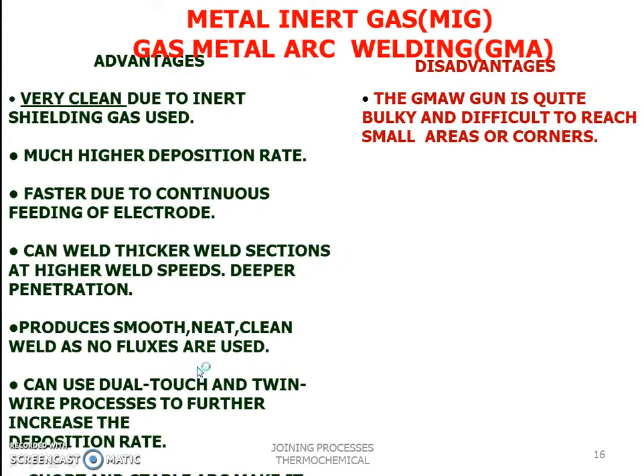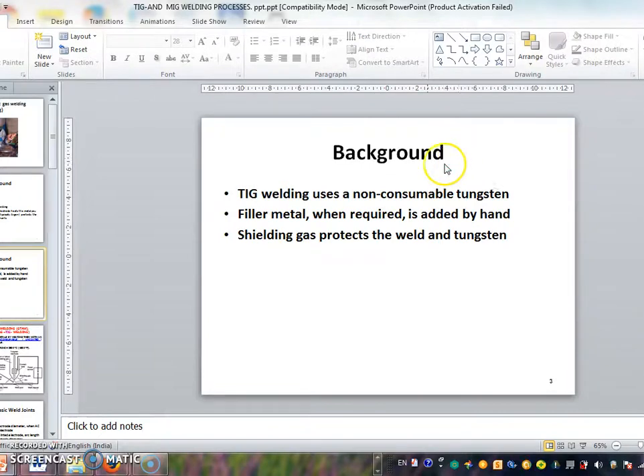The advantages and disadvantages of metal inert gas welding. It is very clean because inert shielding gas is used, with a much higher deposition rate, faster due to continuous feeding of the electrode. It can weld thicker weld sections at higher weld speeds, with deeper penetration, and produces a smooth, neat, clean weld as no fluxes are used. It can use dual torch and twin wire processes to further increase the deposition rate. The disadvantage is the gun is quite bulky and difficult to reach small areas or corners. Okay, this much is the